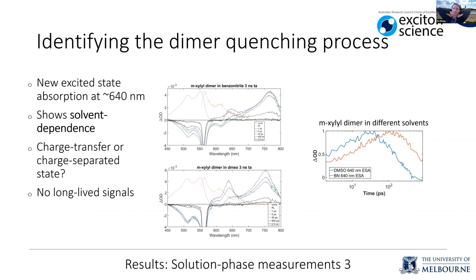Right, so in the transient absorption, the main difference that we see in the dimers is that there's a new excited state absorption that forms here at about 640 nanometers. And this feature shows solvent dependence, so that indicates that it's something like a charge transfer state or a charge separated state, or something with a dipole, because it's affected by the dielectric environment. And so you can see here, I've just got those two traces over the top of each other, but on a log scale, and you can see that they form at different rates depending on the solvent, so much faster in DMSO compared to benzonitrile.